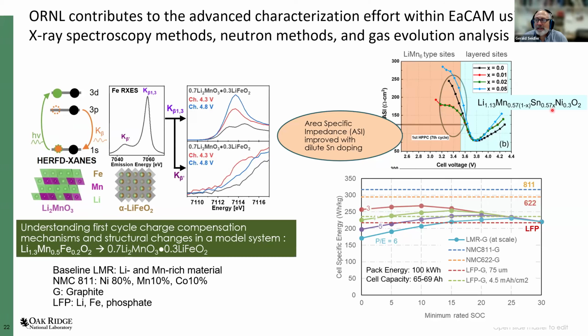Okay, but is the tin at the grain boundaries electrochemically active, or is it just changing impedance like a short resistor? What role is it playing microscopically? The impedance that we are measuring here is a cell level impedance. Essentially, we are improving the kinetics of lithium transfer, the lithium migration within the material. And the grain sizes have become such that the lithium is able to traverse from one grain to another without hitting bottlenecks within the grain.